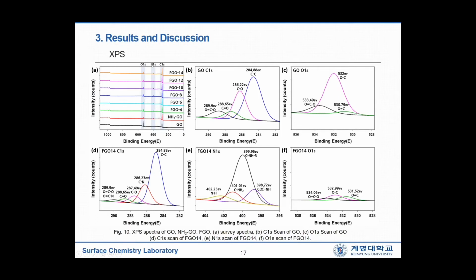the N1s peak, which has not been observed in the GO sample, appears at 399 electron volts. Therefore, we can know the amine group is successfully attached to the graphene oxide sheets. These results are also confirmed in the following high-resolution spectra B, C, D, E, and F.